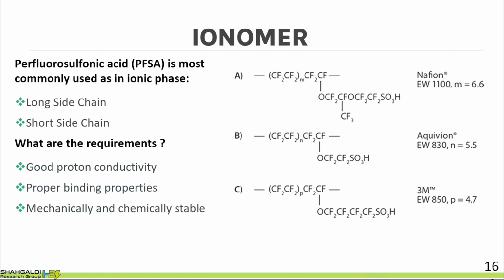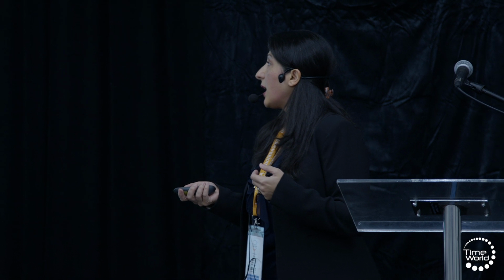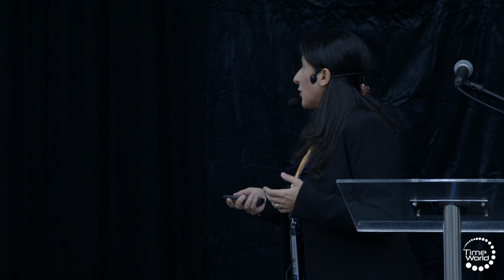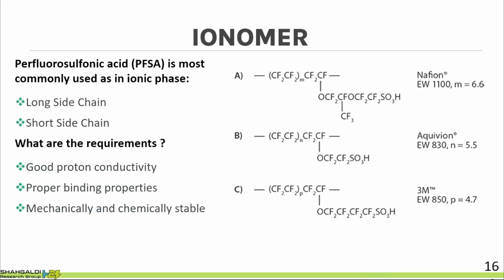So the state-of-the-art ionomer that we are using now is a PFSA, perfluorosulfonic acid. It's a fluorine-based material. We have two ionomers, long side chain and short side chain, commercially available. We are going to get rid of the fluorine soon, finding other material, hydrocarbon-based material, but unfortunately hydrocarbon still doesn't have enough durability compared to fluorine-based material. The requirements for ionomer are that they need to have good proton conductivity, a proper binding property, and be mechanically and chemically stable.